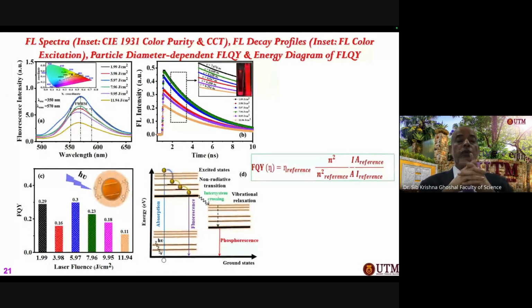So here, to look at what kind of fluorescence you get and at what exact wavelength the fluorescence is happening, we need to look at the color chromaticity map and color temperature, which is called the CIE 1931 color purity plot. In the color purity plot, we see that these nanoparticles are exactly in the purple and violet region, which is the strong part of the region where we can make them very useful for the sensing purpose. And we also calculate the fluorescence quantum yield from some theoretical formula and then match with the experimental results.